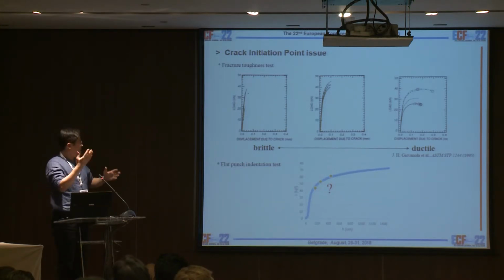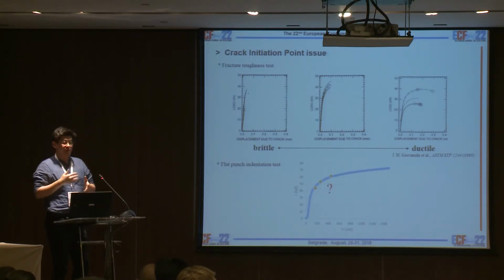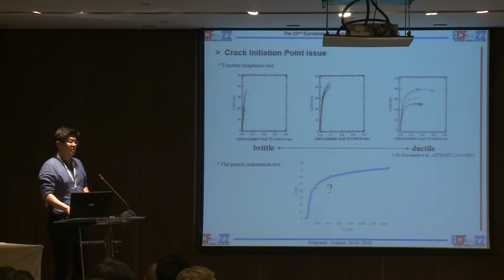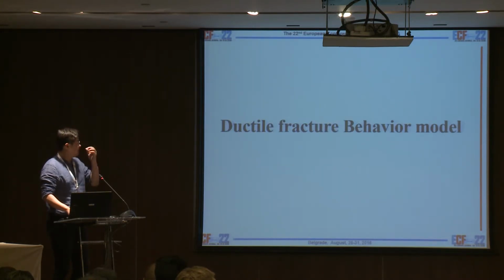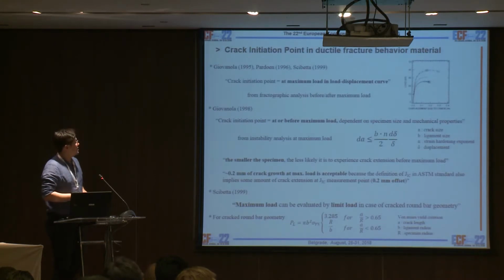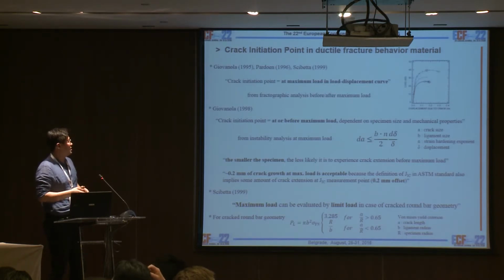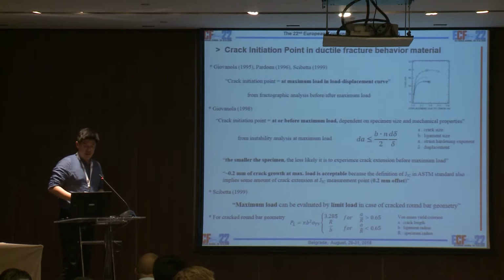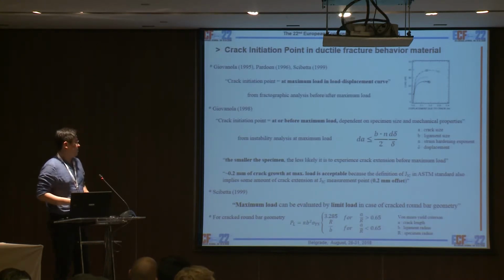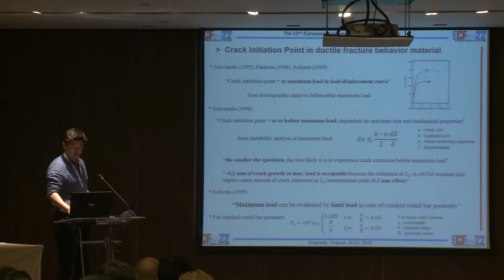Since ductile and brittle fracture behaviors are quite different, we finally decided to separate them into two models, a brittle fracture behavior model and a ductile fracture behavior model. The first one is the ductile fracture model. In this case, we adopted previous researchers' theory on the cracked round bar specimen. They said the crack initiation point is at the maximum load in the load-displacement curve, and the maximum load can be evaluated by the limit load equation shown below.